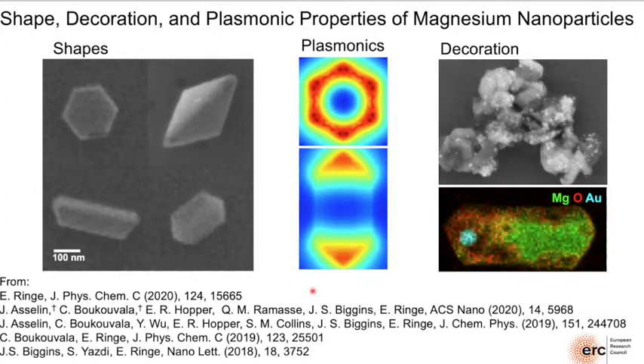Absolutely. So the substrate is unavoidable. When we do EELS maps, we use a silicon nitride substrate. There are effects of the substrate. So for instance, in the cube, you get a proximal and a distal peak, and so on. In the hexagonal plates that we see in magnesium, there is a bit less effect of the substrate, and it's just because the electric field doesn't penetrate the substrate much. There's not much we can do to cancel out the substrate effect.